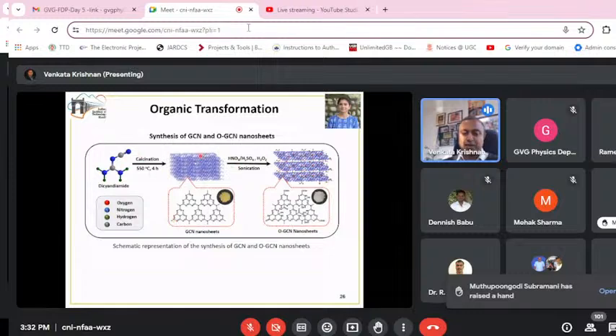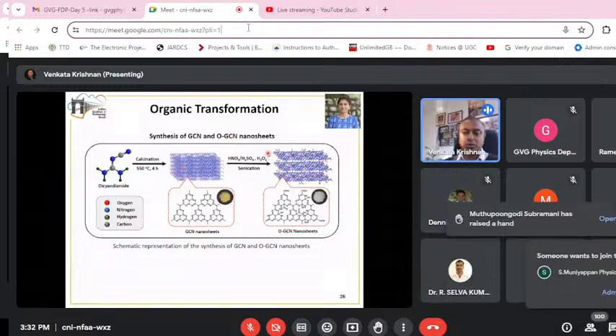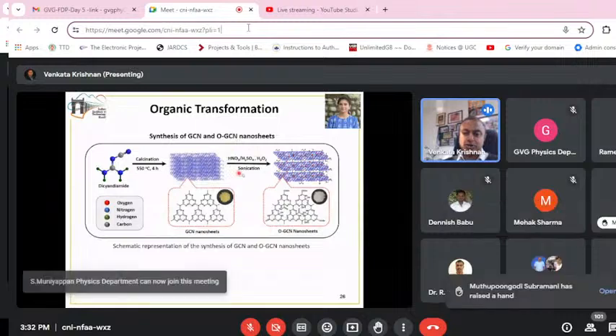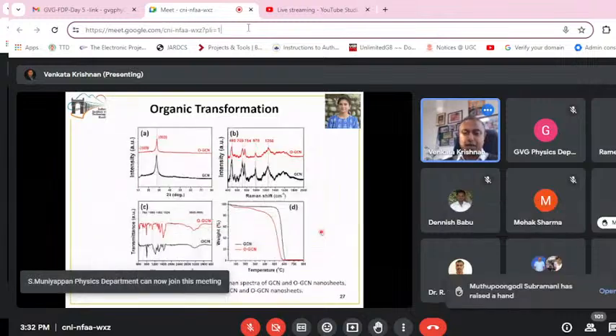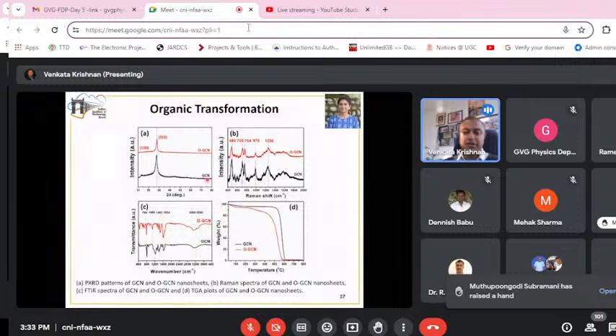First, we prepared the graphitic carbon nitride using a simple calcination, which is a polymerization reaction, and then using H2O2 as the oxidizing agent, in the presence of HNO3 and H2SO4, we prepared the oxidized form of graphitic carbon nitride. Similar to the previous work, we did a detailed characterization of the material using XRD, Raman spectroscopy, FTIR spectroscopy, and TGA to understand the presence of functional groups, the structural integrity, what type of structure is formed, and the thermal stability of the catalyst.